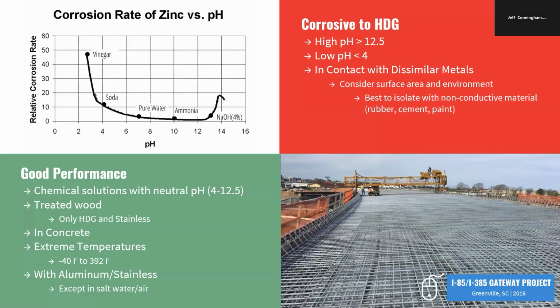We like this slide. I just tried to sum it up for you, if you take anything away: what is corrosive to hot dip galvanizing, and what is really good performance. Corrosive are going to be your highs and low pHs, anything above 12.5, anything below 4. And then in contact with dissimilar metals, it's been done before. You have to consider how much surface area is actually touching and in the environment. Most of the time, it's best to isolate with a non-conductive material, a rubber, cement, paint, something like that.